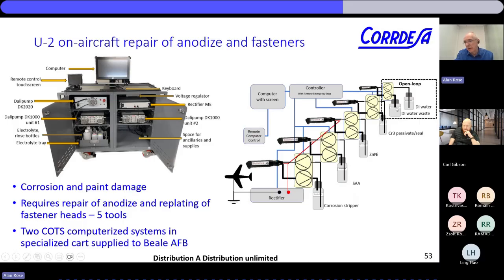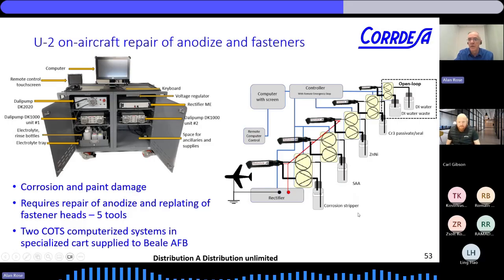This is a more complex process, so we're putting a computer interface there because we're doing an electrolytic strip with one tool, and then we stop. The computer tells us when to stop. Then we do an anodize. You anodize the aluminum, and that essentially masks the area around the fastener. And then we do a zinc nickel over the previous cadmium or bare fastener, and then passivate and seal and rinse, all basically on a mobile system.